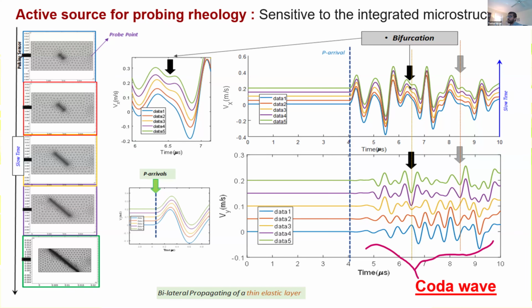But when we start looking at the coda, we start seeing complex but interesting changes in its structure. In particular, you can start to see some small bifurcations. If you look at the blue curve, there's a smooth decrease, versus the green one, where we have the largest area and thickness of the elastic layer. You see small changes in the structure. That's the kind of thing we want to look at: if we can realistically distinguish these small features, that has information about the state of damage within our sample.